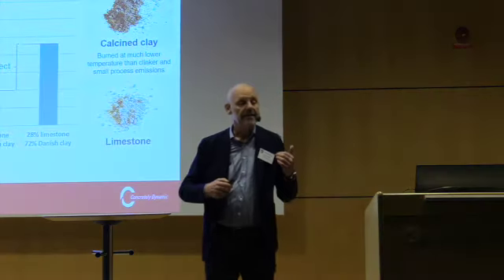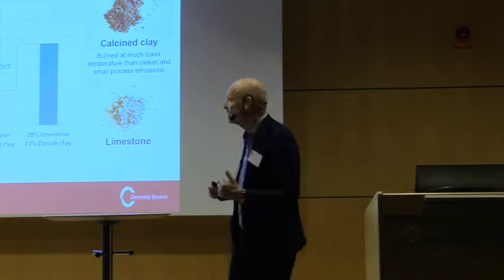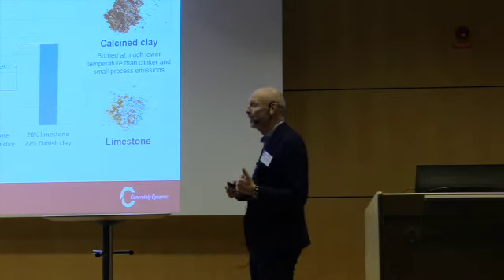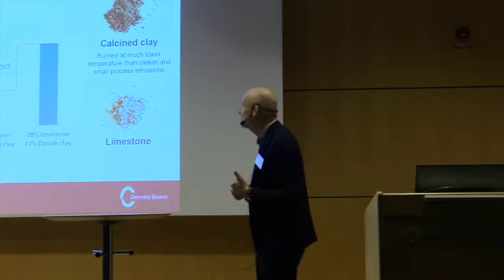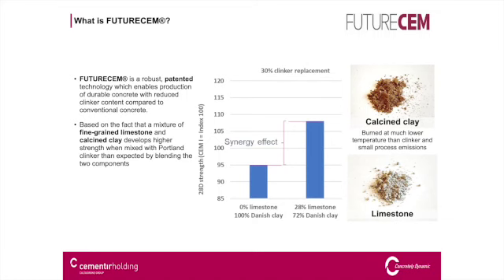And the technology, which is very similar to what the Swiss people call LC3, is basically that if you mix the calcined clay with the limestone, there's a synergy effect, which means that you get a higher strength than you would have had if you used the calcined clay alone, or if you used limestone alone.